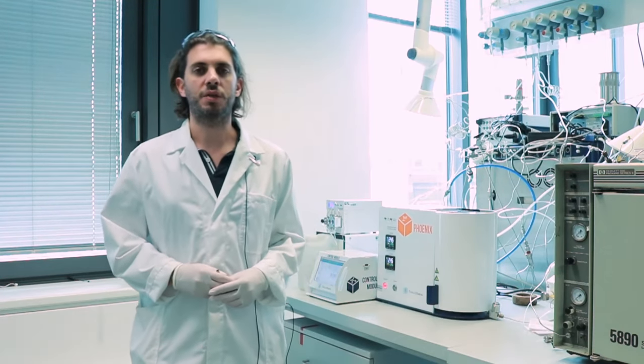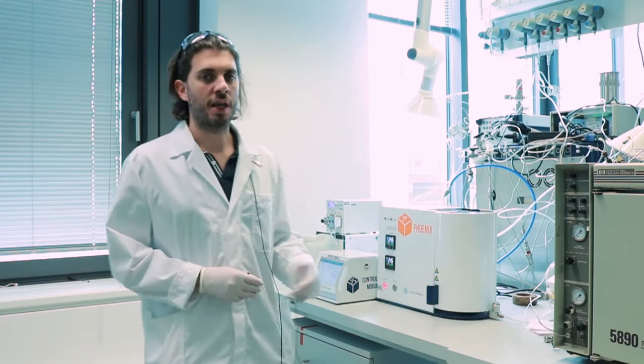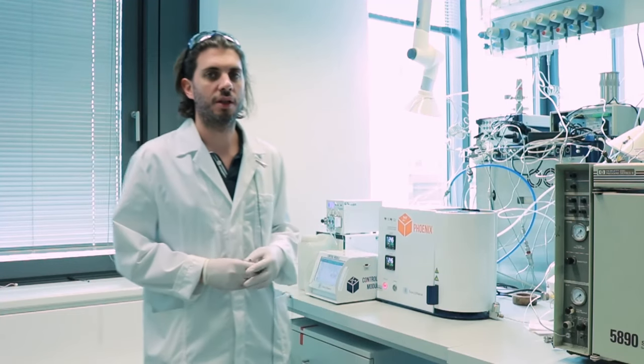The results of the combustion are quite reproducible, which is surprising considering that the combustions are out of control. As we can see from these micrographs, the solids produced with this method are very spongy, which is a desirable feature for a catalyst. However, the obtained products are not always pure spinels, and that is why for many of them the second step of the preparation is a calcination. The solids prepared in this way are used as catalysts in reactions such as the water gas shift reaction, and in this case alcohol oxidation in the liquid phase.